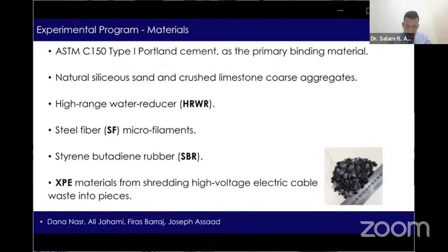Let's talk now about the experimental program. Mainly, let's start with the materials. So ASTM C150 Type 1 Portland cement is used as a primary bonding material along with natural siliceous sand and crushed limestone coarse aggregates, high-range water reducer (HRWR) based on naphthalene sulfonate to improve the workability of the concrete mix, steel fibers microfilaments having 13 millimeters length and 0.18 millimeter diameters, a commercially available SBR, commonly used as a bonding agent, and the XPE material that was obtained by shredding high-voltage electric cable plastic waste into pieces measuring 2 to 12 millimeters in size, as you can see in the picture in this slide.